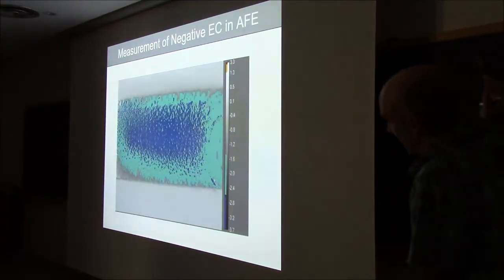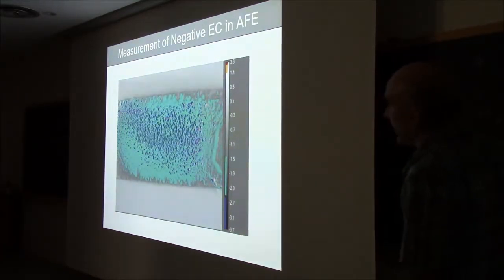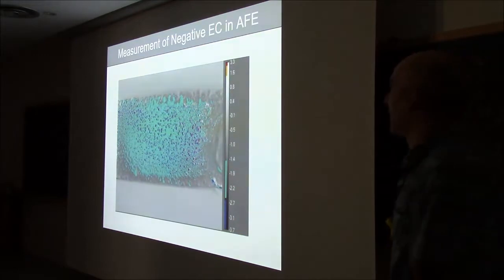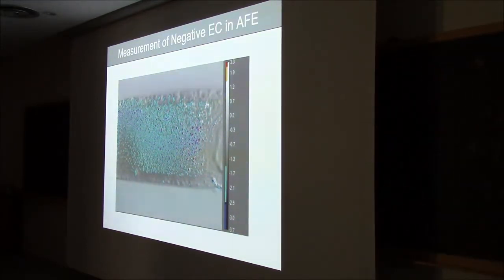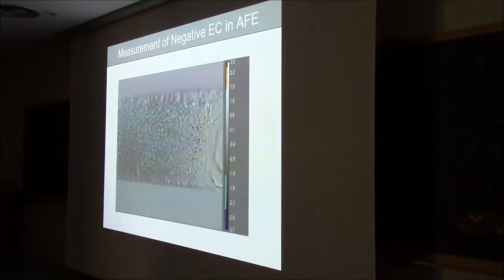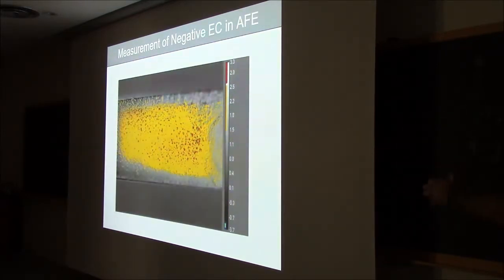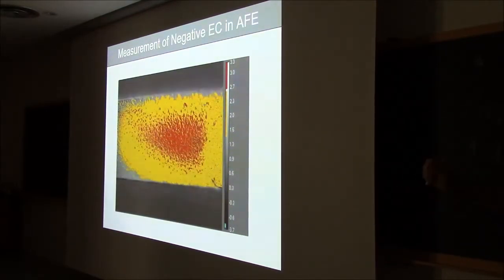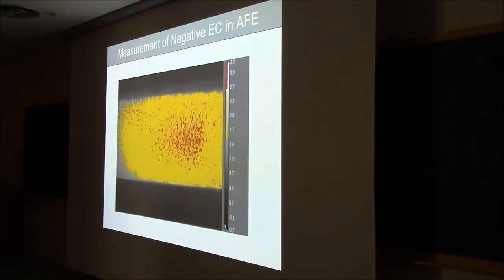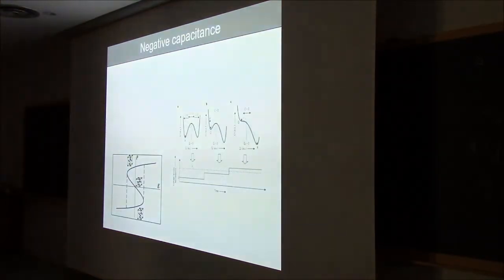So you basically switch the polarization, and as you switch it, you create like a cold front that sweeps across your sample. And the temperature changes that you can get here are pretty big, of the order of 5 degrees, which, I am told by those who know about electrocalorics, is something big, useful. Now 5 degrees by itself is not useful. The thing is you can switch many times and get 5 plus 5 plus 5. And of course when you switch off the voltage, the thing goes back to the antipolar state and returns you the temperature. So you want to switch inside your fridge, then take it out and switch off.